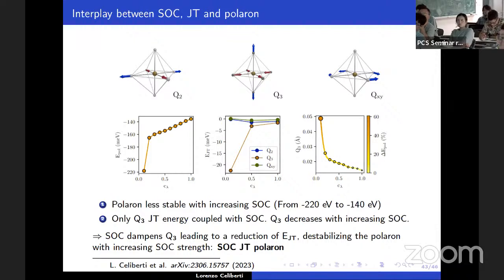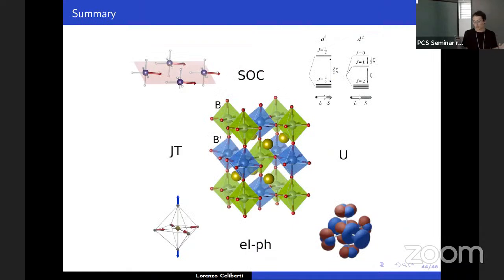So basically, from this calculation, what we observed is that in this system, you cannot really single out the spin-orbital coupling when you try to explain the stability of this polaron, but this spin-orbital coupling and Jahn-Teller effect are really entangled. That's also why we called it a Jahn-Teller spin-orbital polaron. So in summary, I hope I managed to convey this message that in this class of material with strong correlations, strong spin-orbital coupling, you can really have competing interactions, which opens up really interesting physical phenomena.